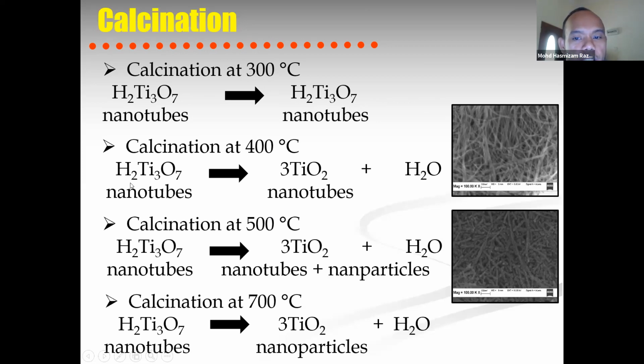Here we can observe the equation. The hydrogen titanate transforms into titanium dioxide nanotubes at 400 degrees C, and somehow after we calcine at higher temperature, we can observe a mixture of nanotubes and nanoparticles of titanium dioxide at 500 degrees C.